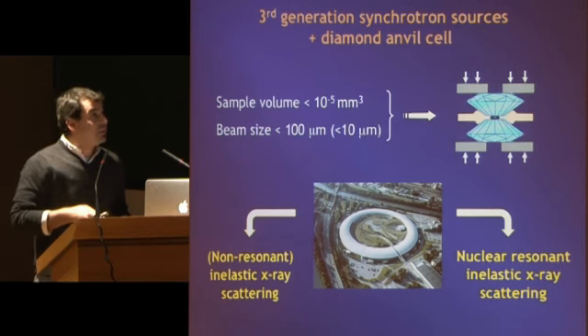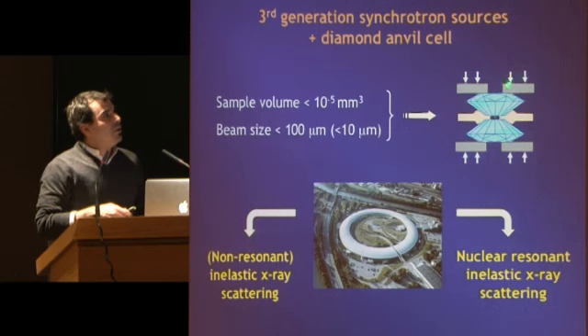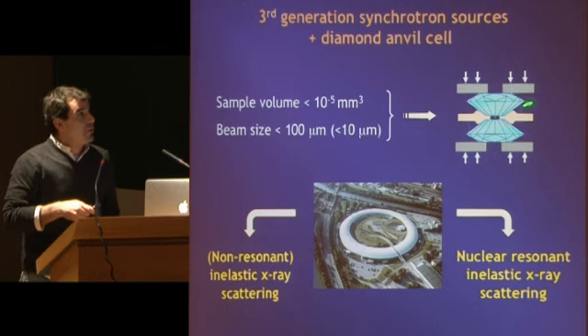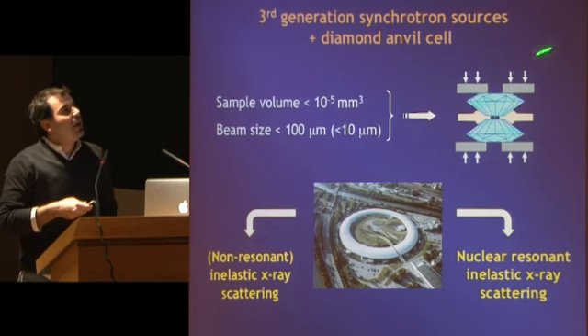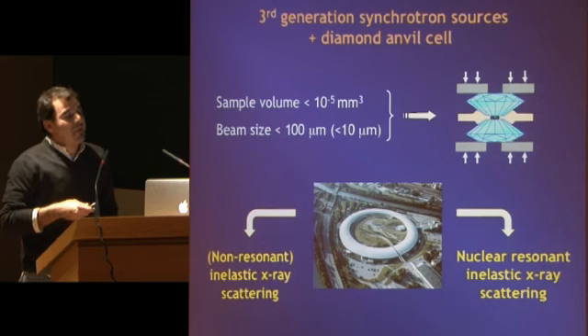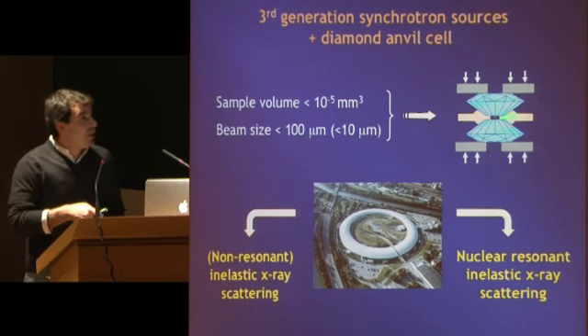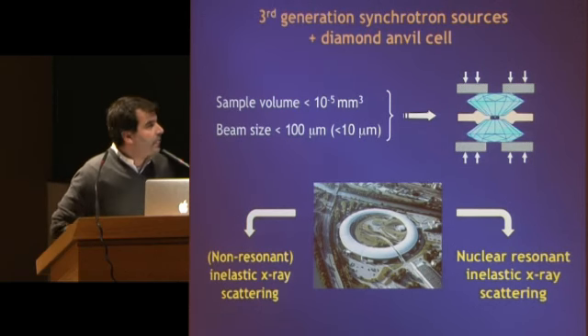So for a relatively moderate force on the upper surface, we can have quite high pressure here. And to give a feeling, for a pressure of about 100 bar here, we might end up with a pressure of 1 million bar here, so a megabar, 100 GPa.